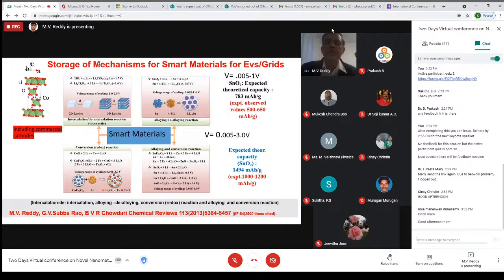Another type of mechanism is alloy based. For example, if you take silicon or tin, it will form an alloy with lithium. Due to this we can get high capacity, about 4.4 lithium extra, but we also get huge volume expansion. This is a bit of a disadvantage. To avoid this, people have used nanotechnology or other types of technology. I don't have time to discuss it now; if time permits, I'll discuss it at a later stage.